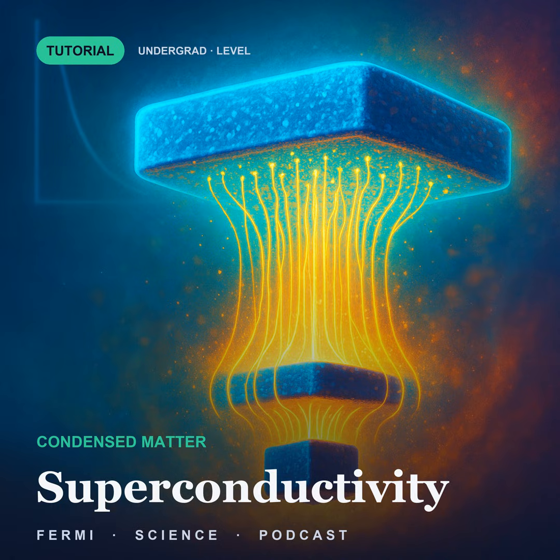Who worked that out? Because a lattice of flux tubes is a very specific thing to predict from a free energy expansion. Alexei Abrikosov in Moscow, and the story is a warning about deference. He had the solution in 1953, took it to Landau, and Landau did not like it, so he sat on it and published in 1957. A lattice of flux lines, each carrying one quantum, packing closer as you raise the field, and he got the shape wrong. A slip in the arithmetic gave him a square.